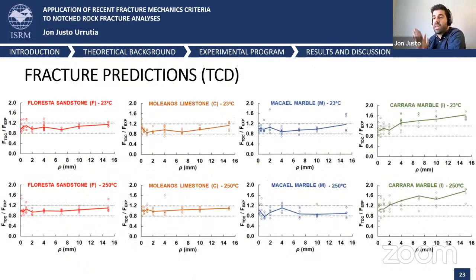And finally, these are the fracture prediction results for each of the analyzed rocks. In this case, for the theory of critical distances, and in particular for the line method. In any case, very similar results are obtained with the point method. The vertical axis of the plots represents the ratio between the predicted failure load and the experimentally obtained failure loads, and the horizontal axis represents the notch radius in all the cases. Dots indicate the prediction of the individual test, and the solid lines the mean predictions.